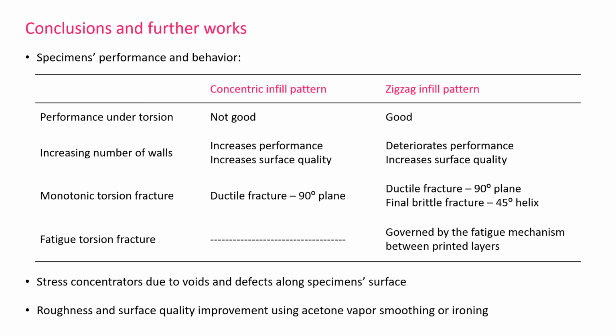Both pattern specimens were characterized by a ductile fracture type in torsion, with fracture occurring in a 90-degree plane with the longitudinal axis, whereas the zigzag pattern showed a more pronounced brittle fracture type with the helix inclined at 45 degrees with the axis, concerning the final fracture stage.